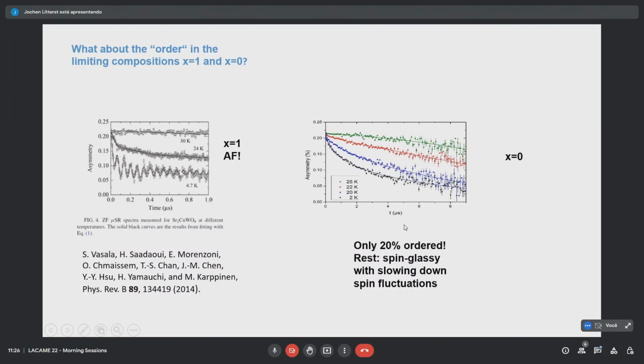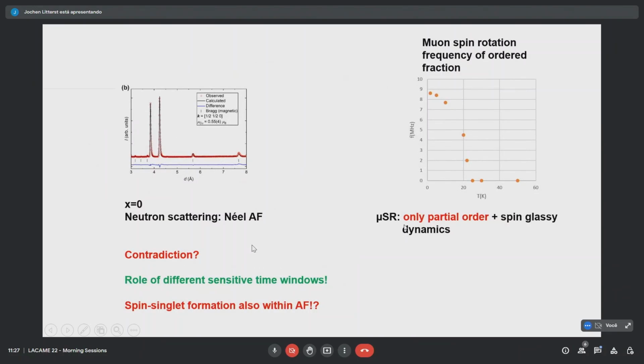We see nice order at low temperature with a well-defined ordering temperature. But if we look at the tellurium compound, we do not see explicit order. We see some fluctuations here, but what we find is that only 20% is ordered. The rest actually is spin glassy with slowing down fluctuations. So that's not a proper antiferromagnet. Now we'll say, yes, it was claimed before; there is neutron scattering with very nice magnetic reflexes. It's an antiferromagnet. Here, from the muons, we see partial order and partial spin glassy dynamics.